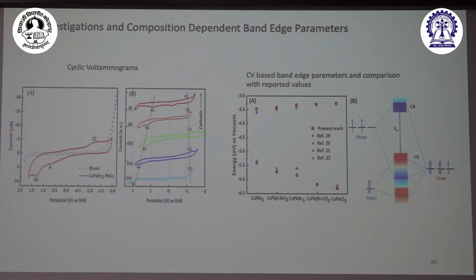Again, there is a cyclic voltammogram based on the composition of quantum dots. Again, there is a shift in the particular valence band edge and conduction band edge. The valence band is changing more than the conduction band edge. That is big, and the red dots are our results, and the blue ones are other authors'. Again, it matches very well. We explain this on the basis of the electronegativity of chloride ions. I don't want to discuss it right now. We will proceed, but there are no new ideas in this result, so I don't want to tell you.